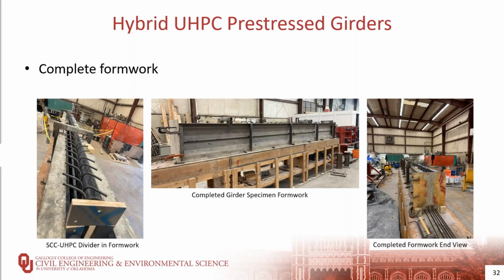After placing the instruments, the other side of the formwork and the end plates were placed, then a divider was inserted at the interface between the SCC and the UHPC. And this divider, you can see it from the figure on the left at the very end. This divider was actually used to help control the flow of the two concretes when casting them. This divider did not block the entire width of the bottom flange, but did block most of the top flange and the web widths.